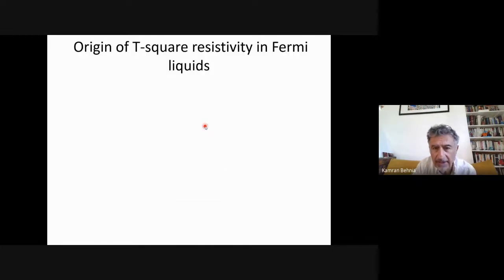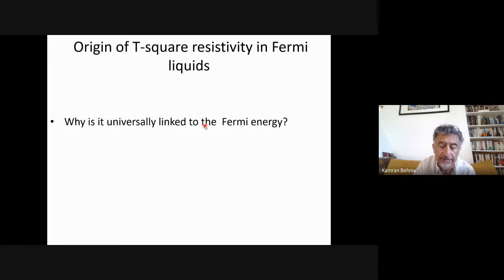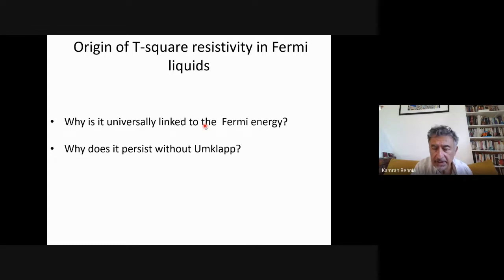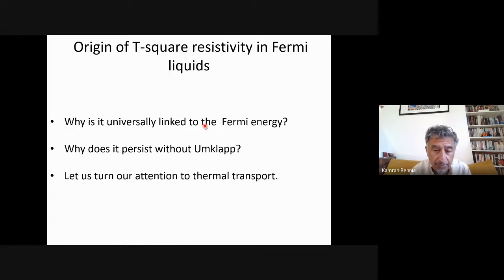And now you see, actually we have a second puzzle. Not only do we not understand why the T-square resistivity persists in absence of Umklapp scattering, the second question is, how come it is universally linked to the Fermi energy? If you have different kinds of mechanisms, which depend on the size of your Fermi surface or the presence of 1 or 2 reservoirs, how come that in most cases, you can predict the magnitude of your T-square resistivity just knowing the size of your Fermi energy?